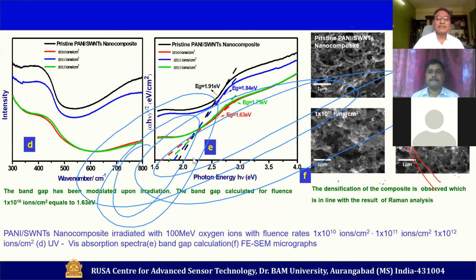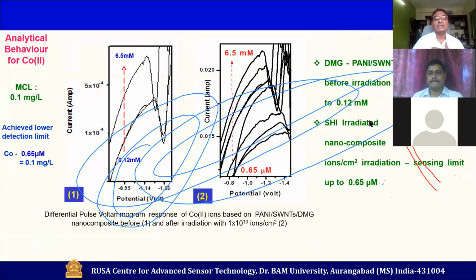And since we were using SHI irradiation, the band gap was very important for us, and engineering the band gap was a very critical point. We could optimize the band gap for 10 to the power 10 ions per centimeter square fluence, which was equal to 1.63. And for that purpose, you can see the FE-SEM images as well. There is a significant increase in roughness of the nanostructured material after increasing fluence rate.